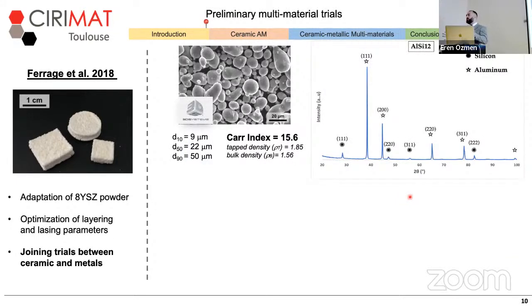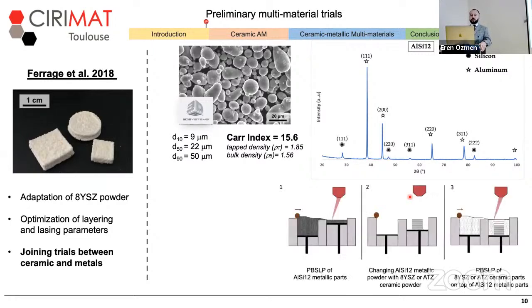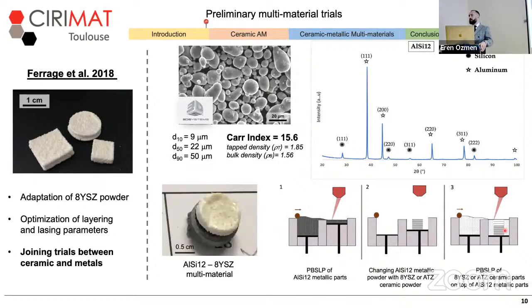Once solid ceramic pieces were fabricated, their combination with metals as multi-material was intended as well. For this, aluminum silicon 12 alloy was preferred as the metal part of the multi-material. Firstly, in a single step, the metallic pieces were fabricated within the same PBSLP machine. Then, by only changing the metallic powder with ceramic powder, the ceramic pieces were fabricated directly on the metal parts. So by this, in a single step, in a single machine, the multi-material was obtained as shown in the example.